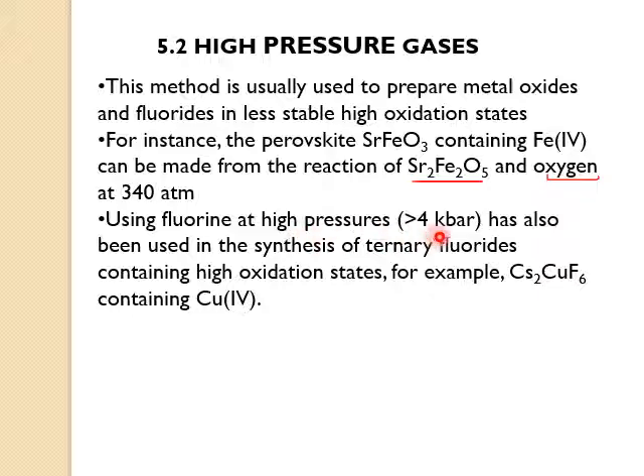Using fluorine at high pressure, that is greater than 4 kilobar, has also been used in the synthesis of ternary fluorides. These are ternary fluorides. So in the above case, the high pressure of oxygen is used, and in the below case, what gas is used? Fluorine gas at high pressure is used for the preparation of ternary fluoride like this compound, cesium copper fluoride. Containing high oxidation state, for example, cesium copper fluoride, the copper normally exists in two oxidation states, but here is copper in +4 oxidation state, which is very rare, less common, unstable, and it can be prepared by using fluorine at high pressure.